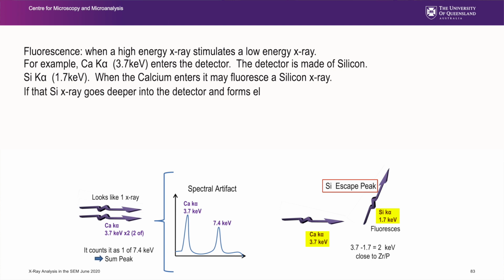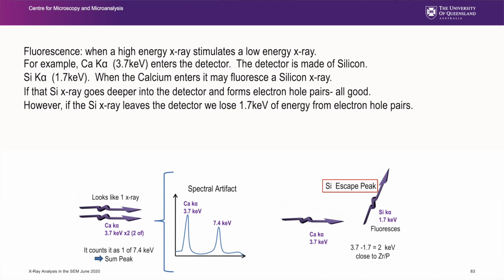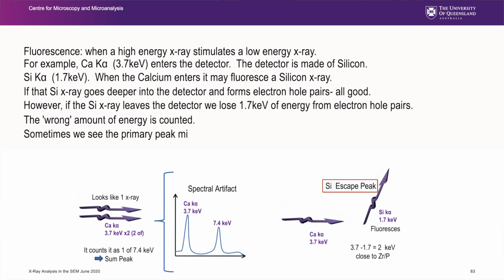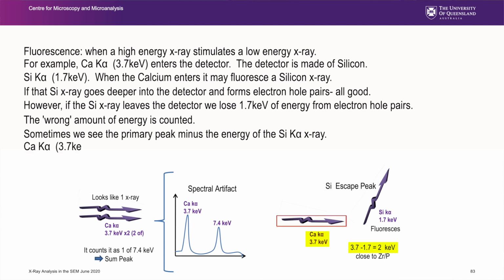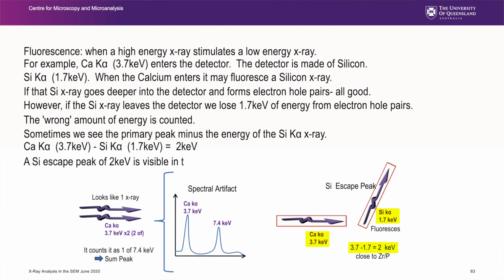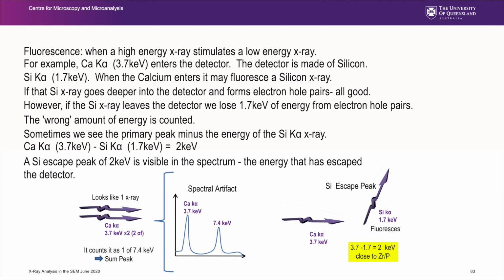If that silicon X-ray goes deeper into the detector and forms electron hole pairs, that's not a problem. However, if it leaves the detector, I've lost that amount of energy from electron hole pairs, and so I count the wrong amount. So sometimes you get your primary peak minus the energy of a silicon K-alpha. In this example, 3.7 calcium minus 1.7 silicon produces a silicon escape peak of 2 keV. That is just the energy that sometimes escapes the detector. And it looks very close to a zirconium or phosphorus peak.